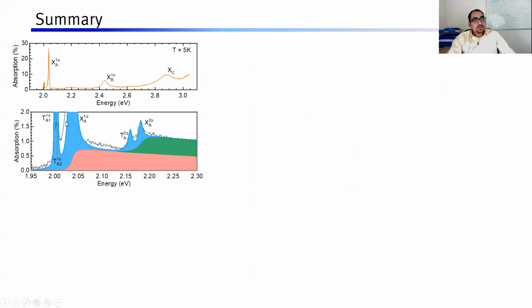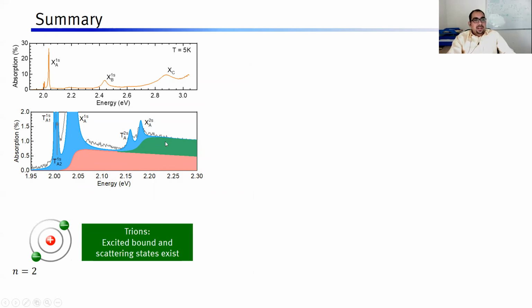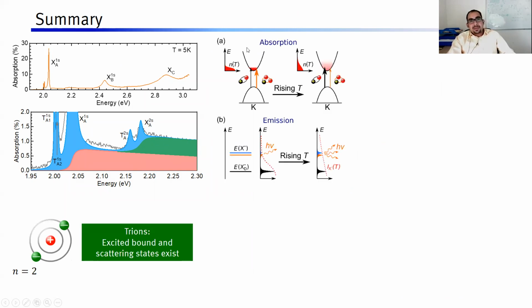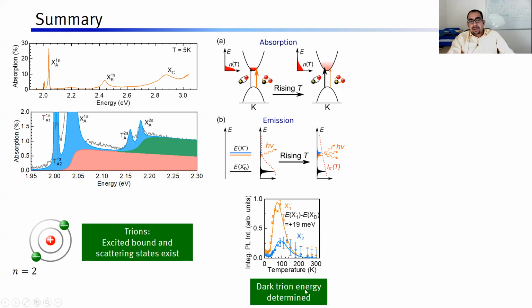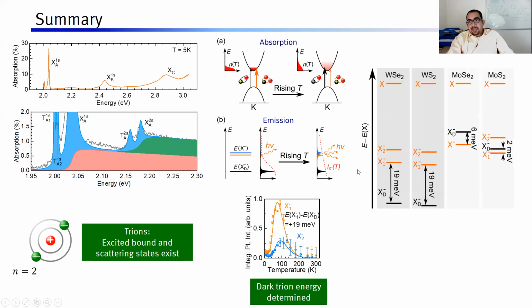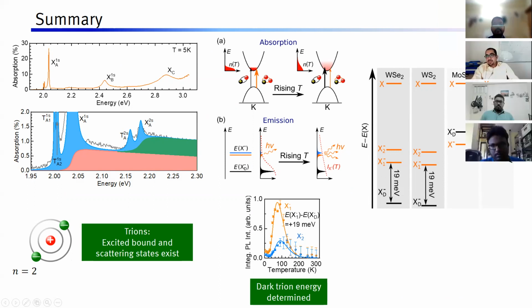So in summary, we have been discussing the ground and excited states of excitons and trions. An excited state of trion was found, and the scattering states of excitons and trions were found to exist. Then we discussed absorption and emission processes as a function of temperature in the doped semiconductors. And we find that we can obtain the dark trion energy from these temperature dependent optical experiments. And these dark trions are the lowest in energy in tungsten diselenide and disulfide, and they are higher in energy for MoSe2. For MoS2, it's a mixed state.